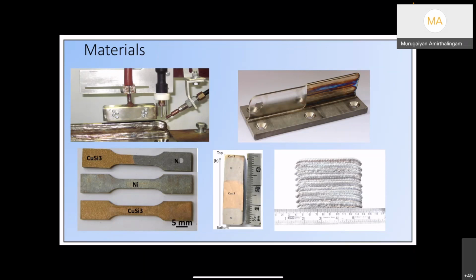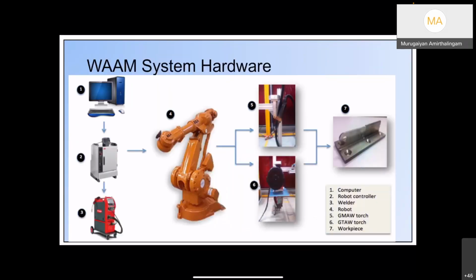So in real additive manufacturing methods, where the functional gradation can be promoted, it is not a sharp interface, so we can also change the composition smoothly, so that it is not like an actual weld. So the entire thing is weld. The entire sample here, what I show here is a weld, but the composition is also smoothly varying across the interface. Good. So any material that is weldable, we can make use of it during additive manufacturing.